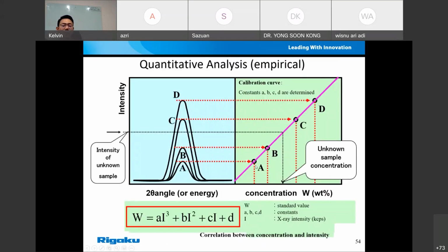As is suggested here, quantitative analysis with empirical calibration means you will need to have a standard to calibrate. So it is very important that you have a good standard, and the standard itself needs to represent what you want to measure. You cannot say I give you a sample, a standard that doesn't contain sodium, and then you want to measure sodium, which is impossible. So it comes to the part of where to get the standard. There are a lot of international standards available worldwide, but unfortunately they are very, very costly. That makes it very difficult if you are not a production site or a manufacturer and you want to buy a standard; it's very costly.